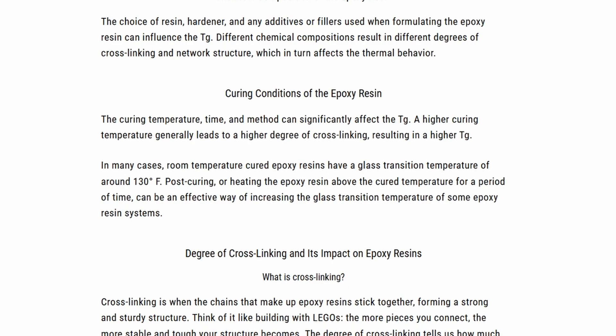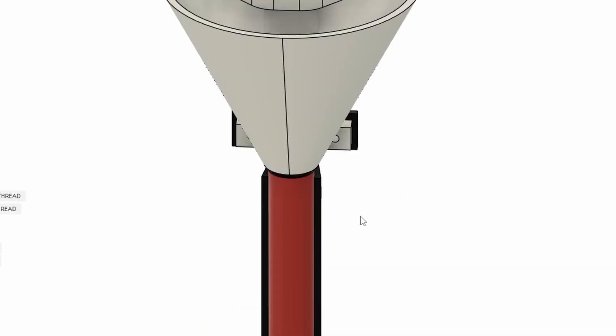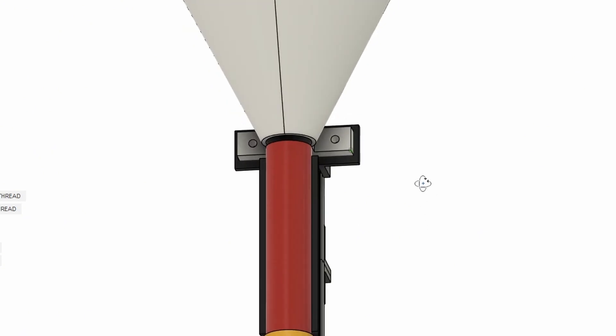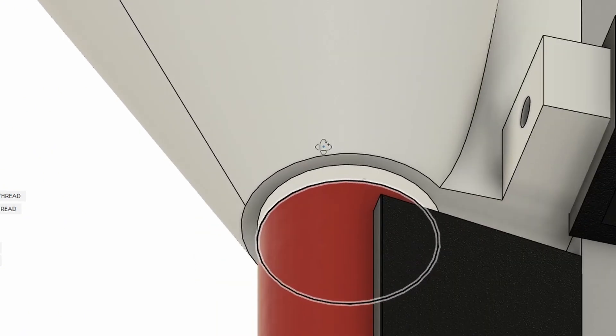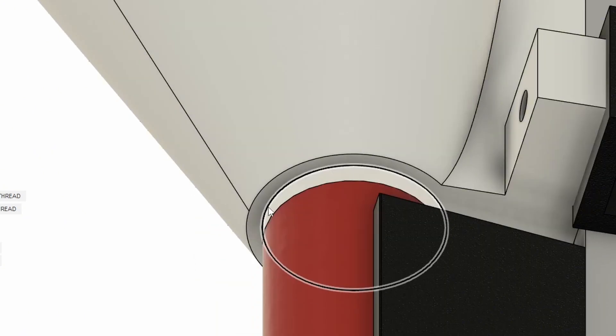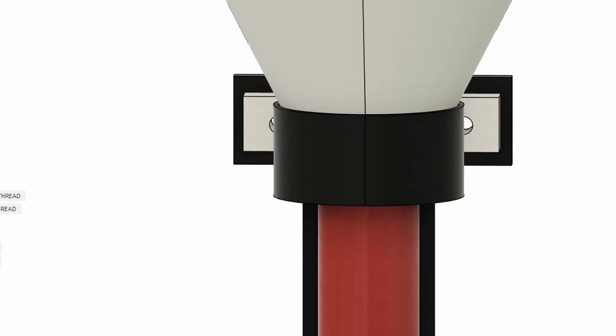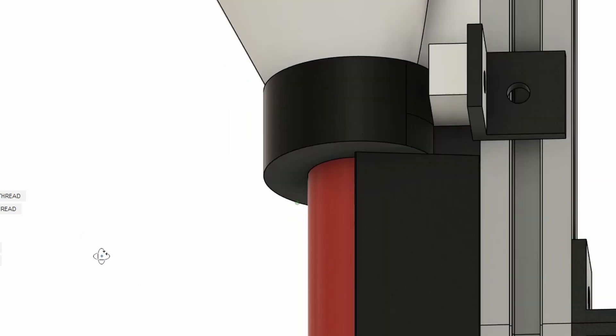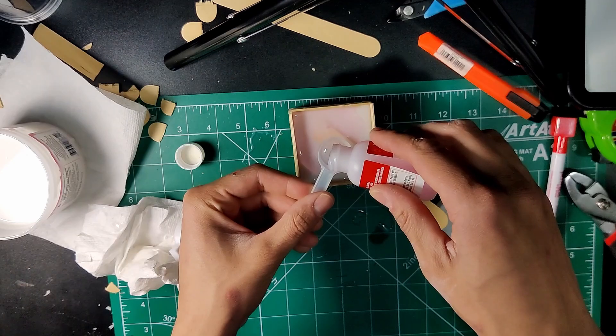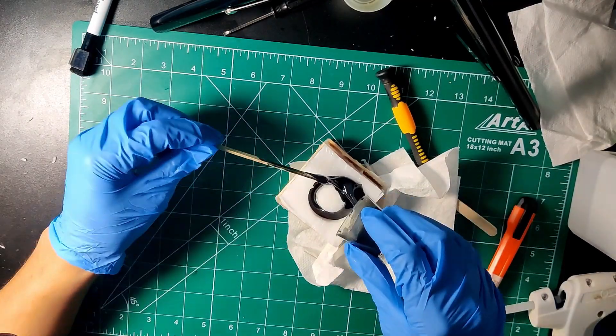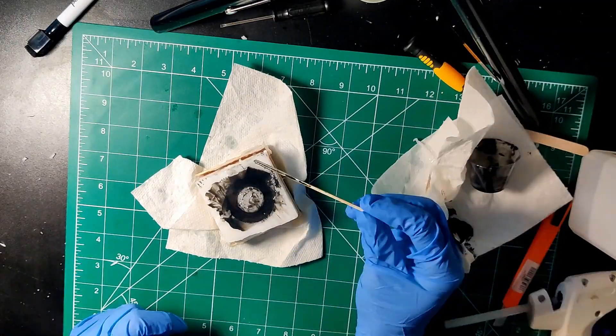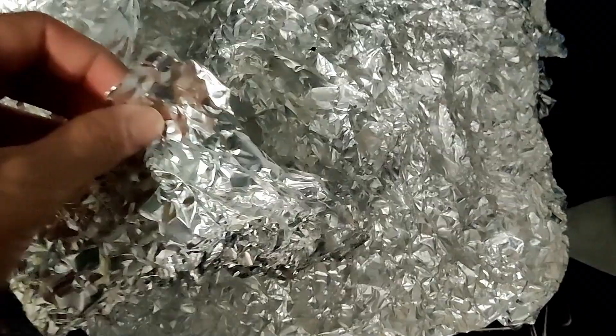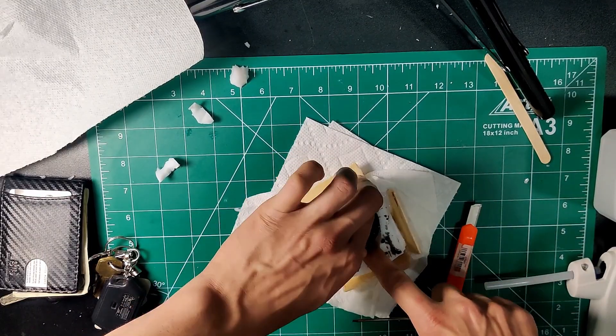After heating up the machine for an hour, I noticed another flaw, which is the funnel deforms around the pipe because of the heat. So, I designed a coupler. And that's where I finally used rubber molding and casted the resin and cured it at 80 Celsius. As of right now, I haven't had any issues with that coupler. So, 80 Celsius seems to be the trick.